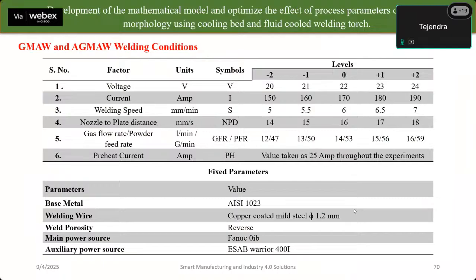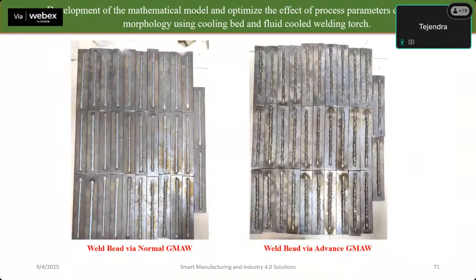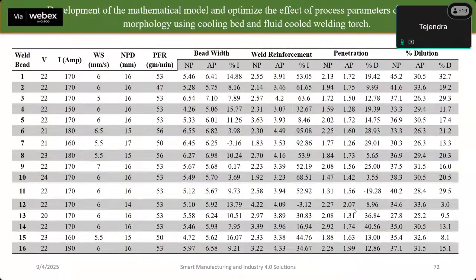These are some of the process parameters that we used for our 3D printing, or the mathematical modeling. For the development of mathematical modeling, these are the weld beads. These are the results. Through the results, we can assure that the weld bead was lower than the normal process. The NP shows the normal process, and the AP shows our process, the advanced process. The increment in the weld bead was not very high. The reinforcement increment was very high. The penetration decrement was good, and the dilution was also on a decreasing trend.